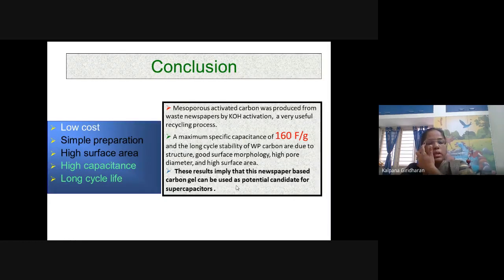To conclude, this mesoporous activated carbon produced from waste newspaper by KOH activation is a very useful electrode material for a supercapacitor, giving a maximum of 160 farads per gram with good cycle stability, high surface area, and good pore diameter.